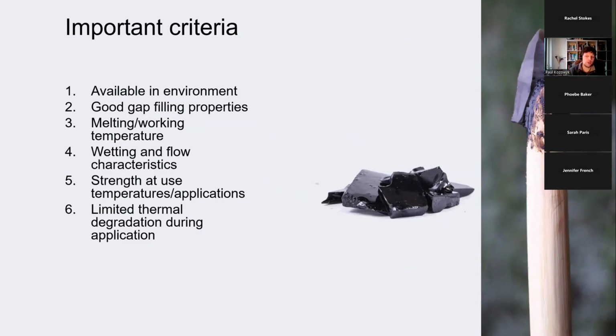This goes along with points 2 and 3, that an adhesive needs to be liquid enough to wet the surface in order for a chemical bond to form, but not so liquid that it just drips out of the joint before it has had time to set. Criterion 5 is probably the most obvious. It has to be strong enough at the temperatures that it's used in. If it's used outside year-round for demanding tasks, it should perform well at those temperatures. It doesn't matter how well it performs at -50, like an adhesive for a satellite. In this case, we're looking at a range from maybe 0 to 25 degrees or something.